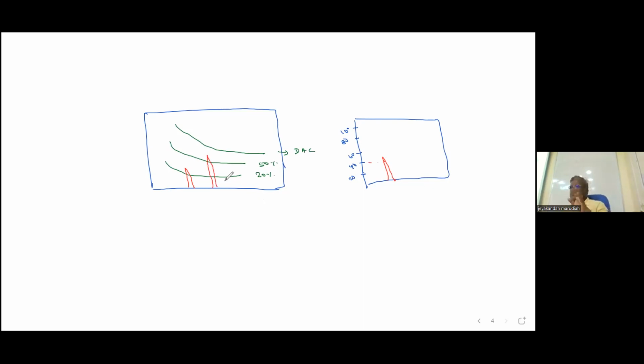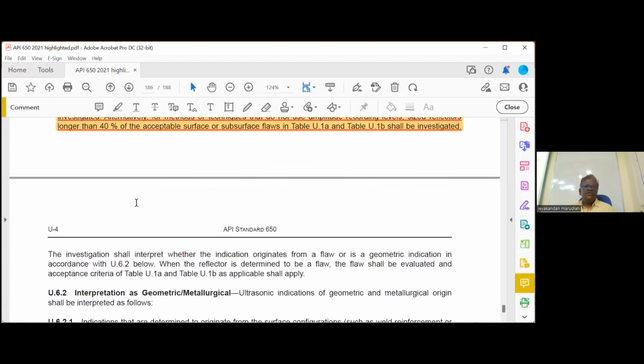Sometimes you can accept it because it is slag. Slag has some acceptable length. When you are accepting a signal which is crossing greater than 50%, or here crossing 75%, then you should record it. You should mention it in the report. There is a signal which is crossing 50% DAC, but it is accepted because of the size. The length is less. So these two points are important. So highlight this one. That is the first point we already noted.